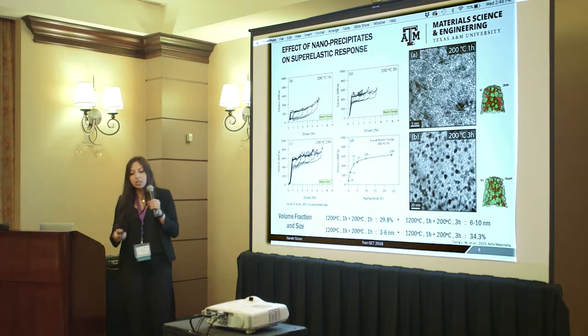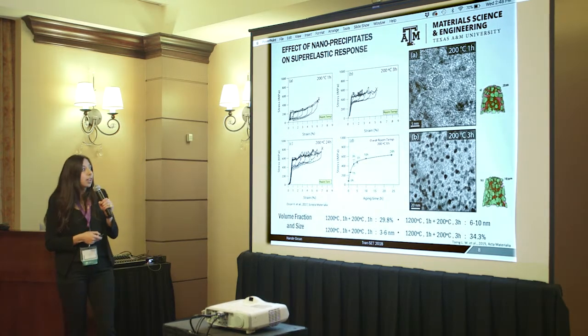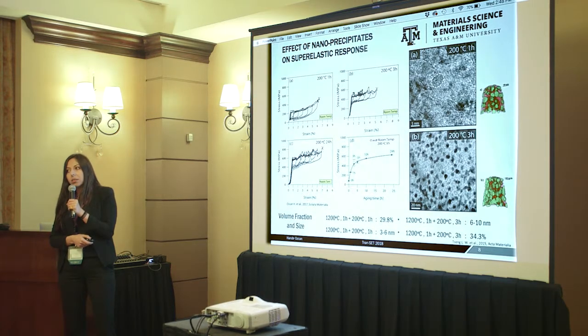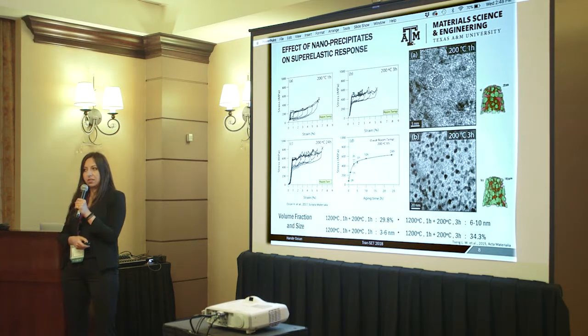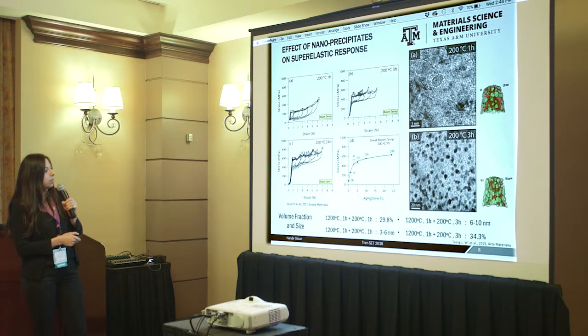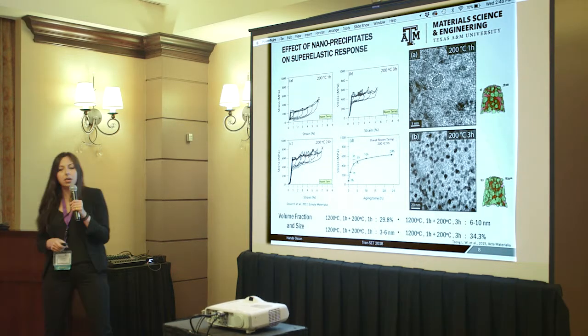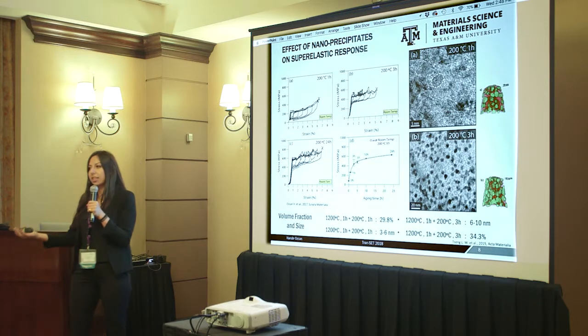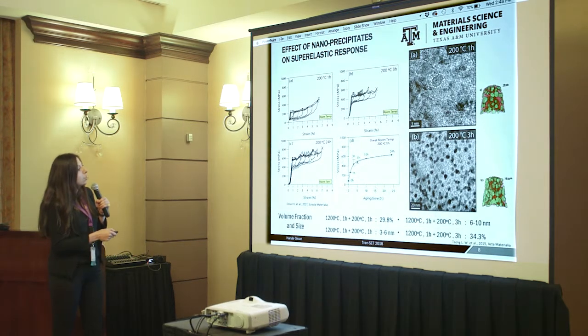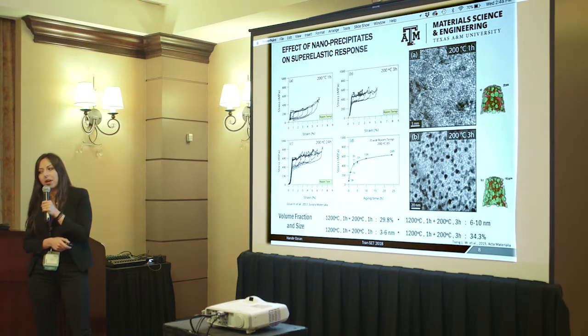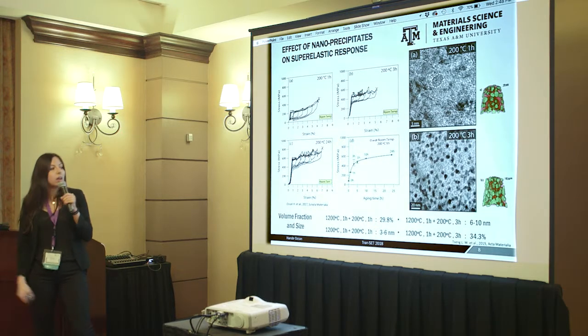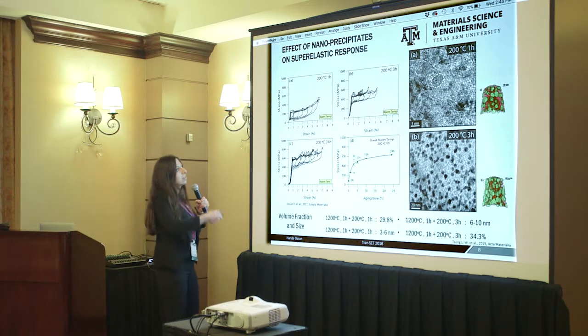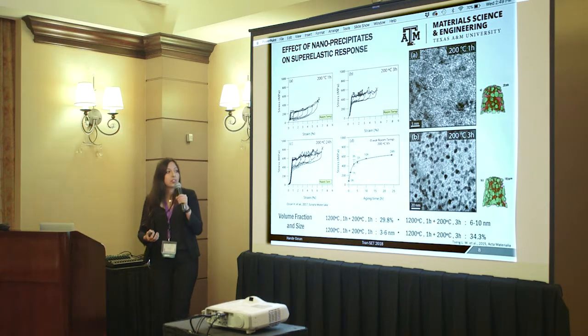So in our group, we realized that you can also change the critical stress by controlling the size of these precipitates. This is our work published in Scripta Materialia last year. If you change the heat treatment time, you are changing the kinetics of the phases, and you can alter this critical stress and increase it up to 600 megapascal. So it doesn't just transform at the same stress. We can change this stress by changing the microstructure.